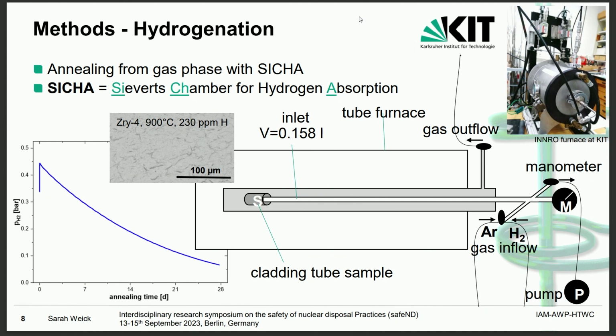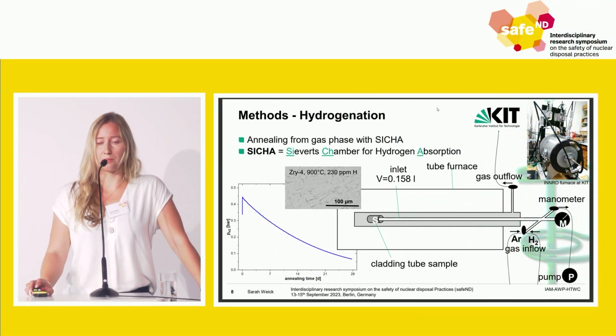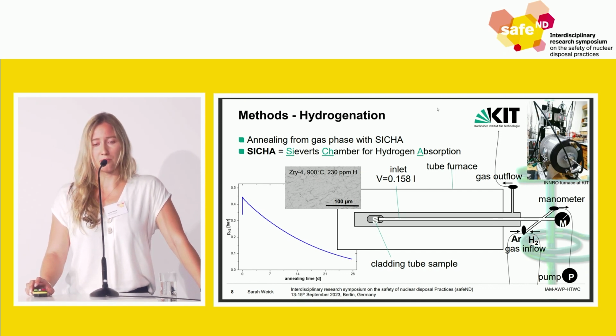This might happen, for example, with our SICHA, the sievert's chamber for hydrogen absorption, which we use for annealing from the gas phase. It's just a kind of tube that is closed, and you can insert some hydrogen gas, and then the sample takes up all the hydrogen, which you can monitor with a pressure drop within this tube.